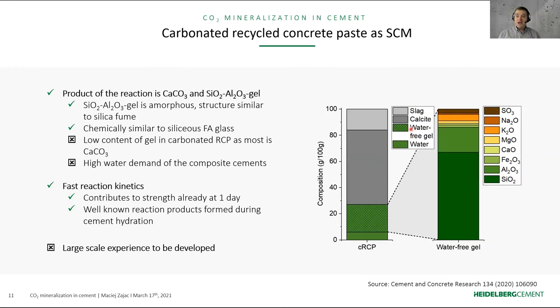However, it's not everything beautiful. You have here on the right-hand side the mass balance calculation of the carbonated recycled concrete paste, and we have performed those experiments in our laboratory. You see here that after the carbonation, the carbonated paste is composed mainly of calcite and unreacted material. And in fact, the content of the gel, as I told you similar to the fly ash, is relatively limited. So this is a kind of disadvantage because we have little reactive material in our new supplementary cementitious materials. However, please note that this is somehow compensated by the very high reactivity of the gel.